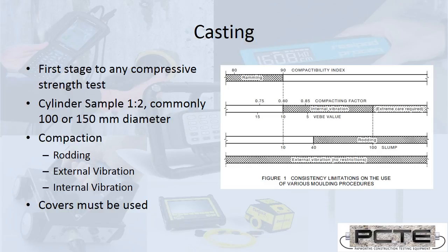A corner case here is that self-compacting concrete is just placed into the mould, allowed to compact, and air bubbles knocked out. The key thing here is that external vibration can be used for any slump flow properties, but when it's appropriate to use rodding or internal vibration is going to be partially controlled by the slump or other factors that affect the compactability of that concrete. So when choosing how to prepare the cylinder on site, an appropriate method of compaction must be used. If we don't compact the cylinder correctly, it's not going to correctly represent our strength no matter how we cure it or break it. Finally, the Australian standard does define that those cylinders need to be covered to prevent loss of moisture.